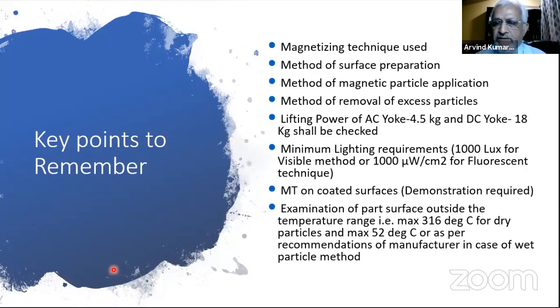Minimum lighting is 1000 lux for visible, and for fluorescent 1000 microwatt per centimeter square. Demonstration on uncoated and coated surfaces is recommended, I would say. You should not go ahead without actually doing a demonstration.